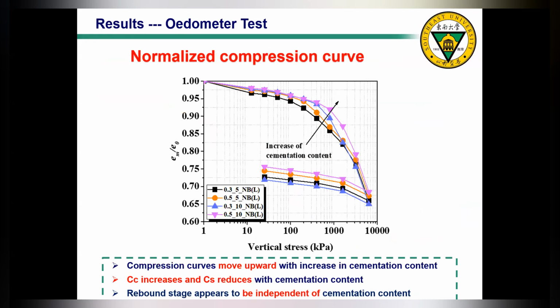Okay, so finally, it's the oedometer test, or one-dimensional compression test. From this test, we can obtain the compression curve. Here, because the soil samples have slightly different initial void ratio, we perform the normalization. So the vertical axis will be the normalized void ratio, and the horizontal axis, the vertical stress. From the black one to the purple one, the cementation level increases. So from the graph, you can see that with the increase in cementation content, the compression curve generally moves upward. So the transition becomes more steep, more abrupt with the increase in cementation content.